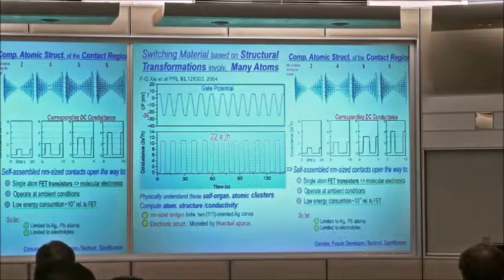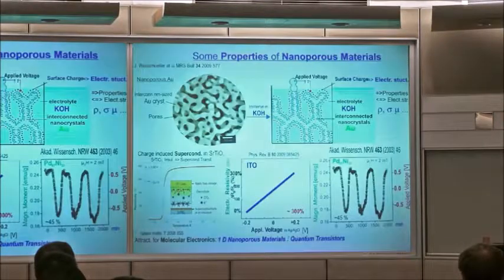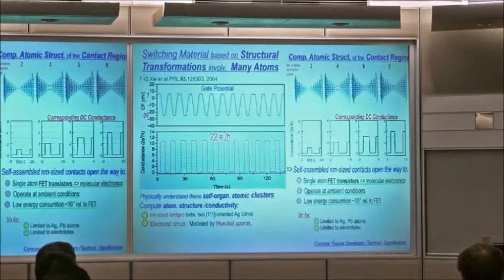Yeah, but the pore size is very small. Well, it's two atoms. 2, 4, 6, 8 atoms. It's not a hole. There's a difference. You know, in this case, when you go to here, the pore is a three-dimensional hole. And the charge is sitting at the surface of the entire metal. And here is the thing, and the charge is sitting here, but what matters is only this contact region where you have 2 atoms, or 4 atoms, or 6 atoms. That's one-dimensional. So it's not a long row, it's just the contact between the 2 cones. And that forms spontaneously.